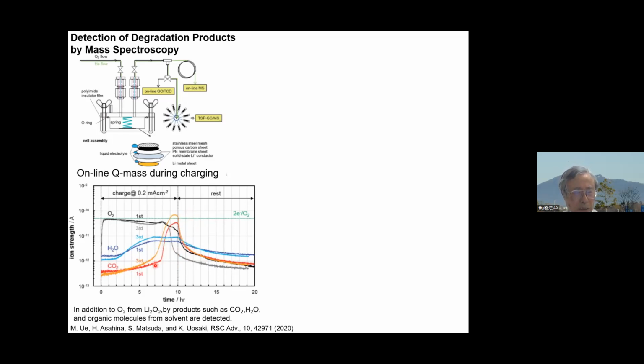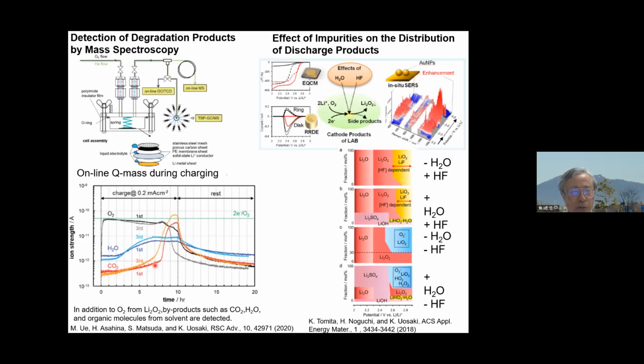So this is one of the causes of the degradation. We also carried out various techniques to detect the impurities: electrochemical quartz crystal microbalance, which I showed before, to see how these products adsorb on the surface; rotating ring disk, by which how much oxidation or reduction efficiency can be determined; and in situ Raman spectroscopy to determine what is on the surface, not only the Li2O2, but also the other products.